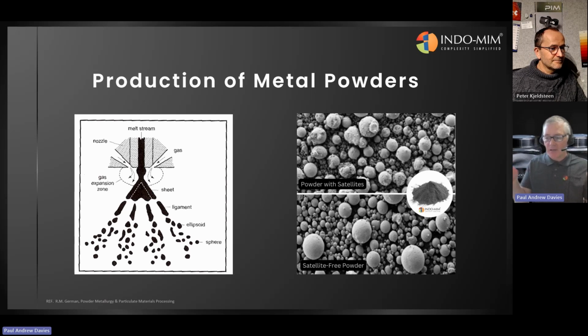So Indomim introduced a secondary ring of gas below the primary atomization to limit the recirculation, and this seemed to be very effective at preventing recirculation. And that allowed the powder particles to form satellite free, which of course can affect its flow characteristics, which are pretty important for certain applications like laser powder bed fusion and binder jet printing in particular.